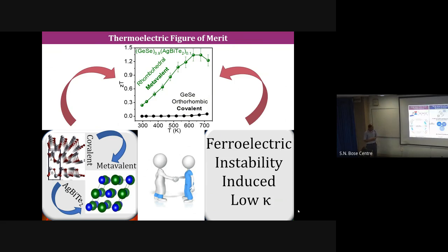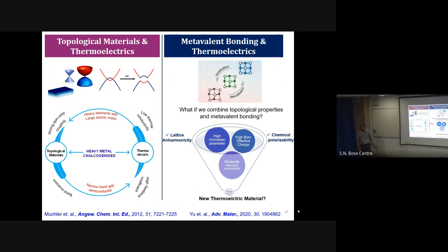So in the next example, I'll come back to this slide. Purely ferroelectric and conductivity should not go together. But this is that fundamental problem. Leakage, yes, leakage will happen. The thing is that if you measure a pellet, you will not get ferroelectricity. So basically we have local ferroelectricity. But do you think it's surface ferroelectricity? We don't know whether it's local or surface because it can be tracked only by PFM. But we see basically low energy optical phonons, which are actually ferroelectric. And these are macroscopic parameters. How the local ferroelectricity will affect them is very hard to visualize.